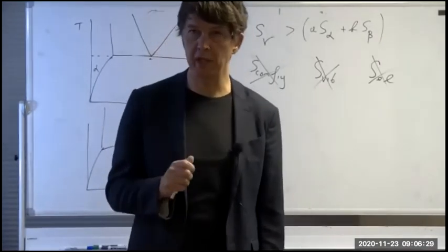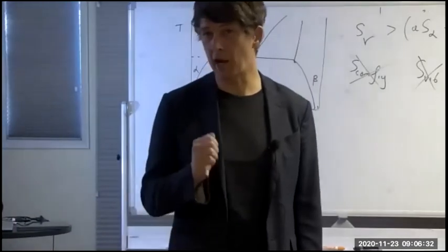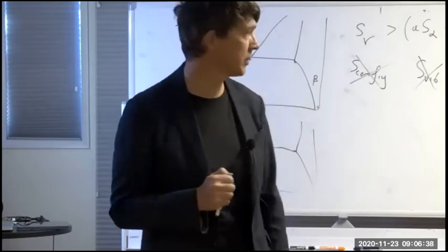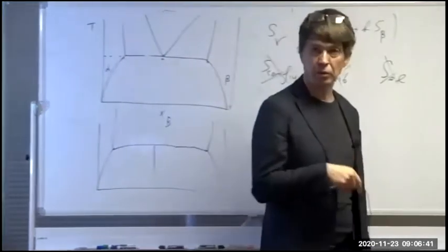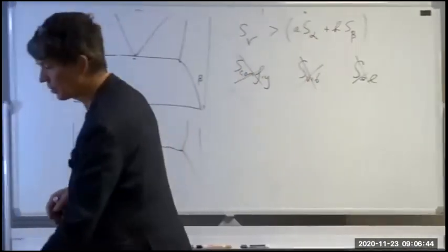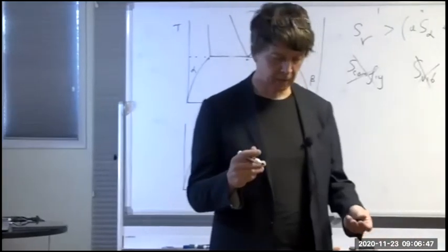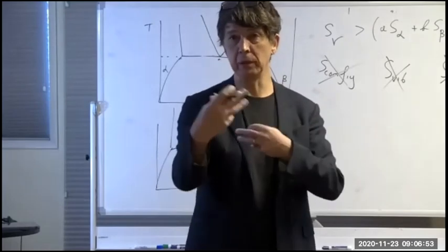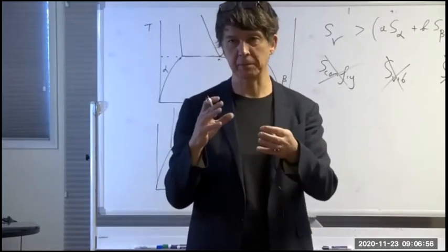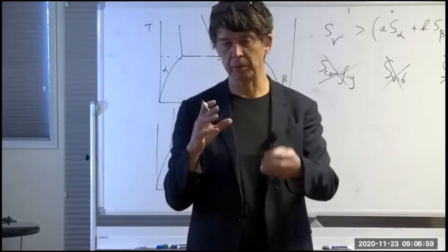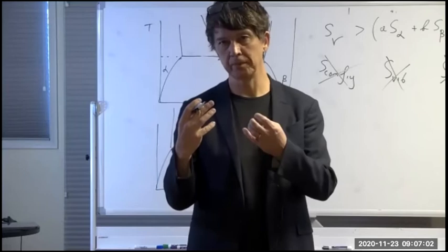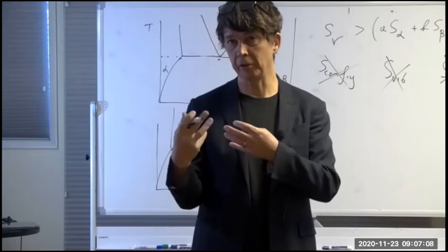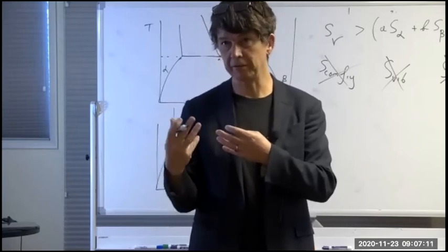People used to always think that the solid solution had the higher vibrational entropy. But that has turned out not to be true when people investigated it carefully. People have investigated by doing neutron diffraction and getting the phonons. The idea was fairly straightforward. The idea was, well, in a solid solution, atoms are not perfectly bonded because you don't always have the environment you really like. Whereas in a compound, every atom tries to get as much as possible the environment it wants for bonding. And so therefore, in a solution, you would expect the bonding to be somewhat less perfect, which is why it has the higher enthalpy, right? And therefore, you would expect it to be less stiff. Less stiff means higher vibrational entropy.